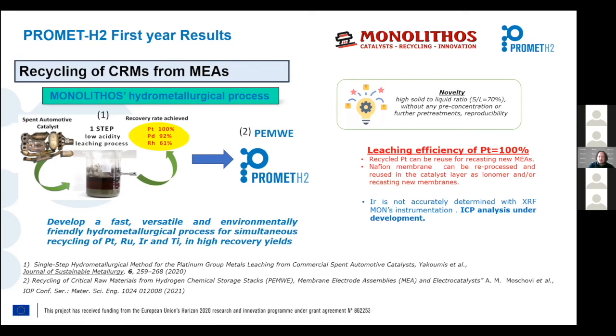I think they did a really great job. You can see here the publication in which they show how they do the process and how they apply the hydrometallurgical process to the PEM water electrolyzer. And we have some data that say that the leaching efficiency for the platinum is approximately 100%. It recovers the platinum completely.